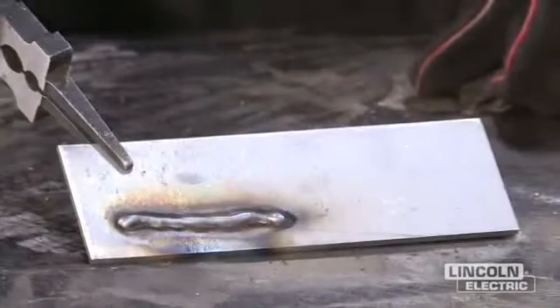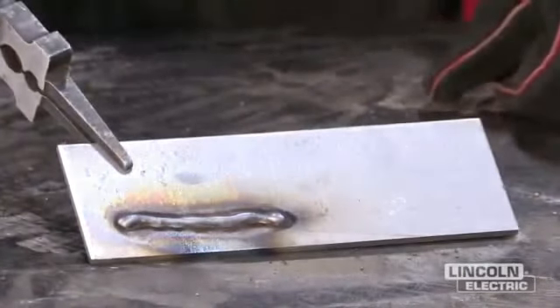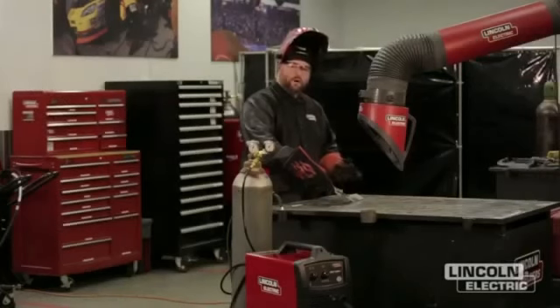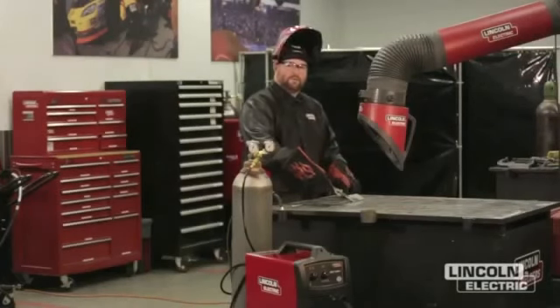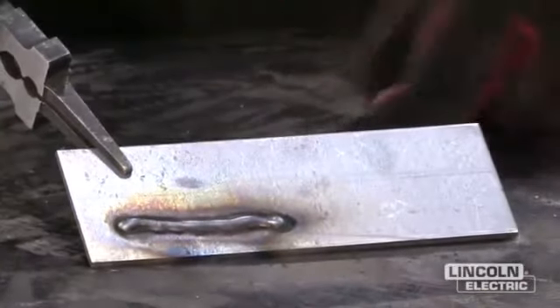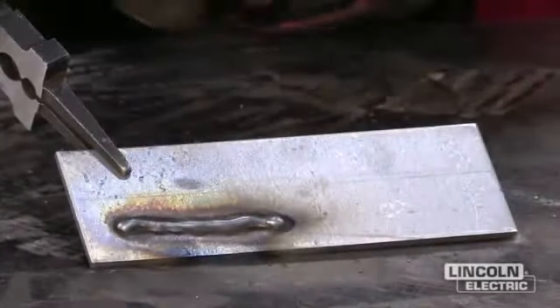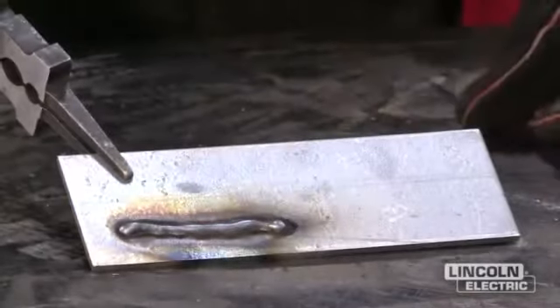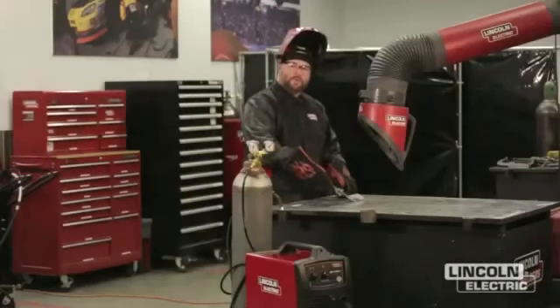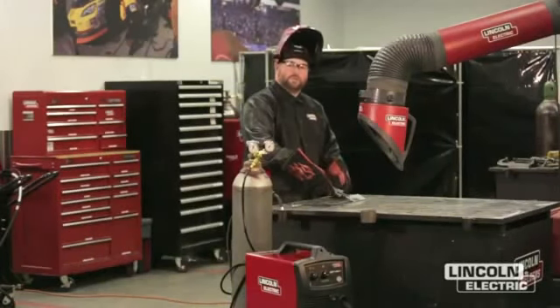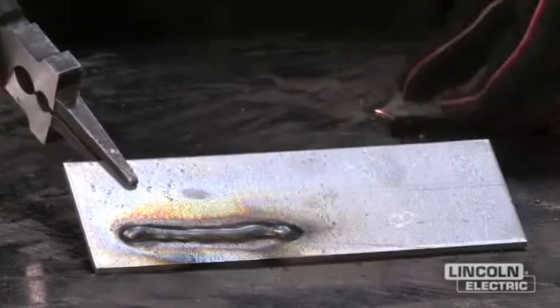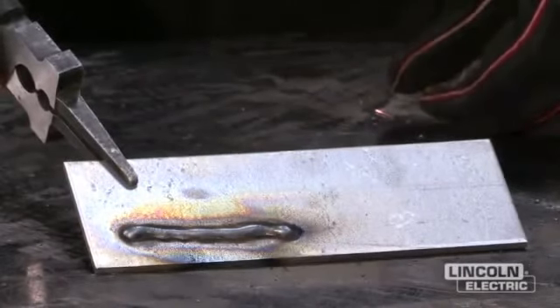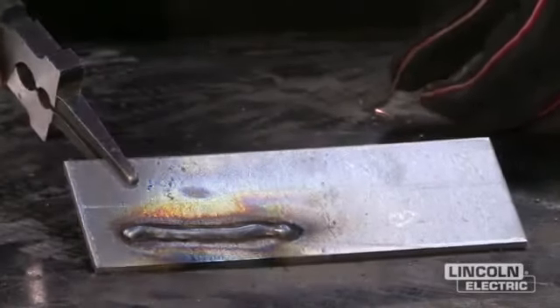So we just made our MIG weld with too long of a contact tip to work distance. First of all, as that contact tip to work distance gets longer, our current goes down. So you can see our weld is real convex and humped up in the middle, and it did not wet out very well. And what will happen with the GMAW process, if you get too far away, you'll eventually lose your shielding gas and you'll end up with porosity in the weld. So we want to maintain approximately 3/8 of an inch for our contact tip to work distance.